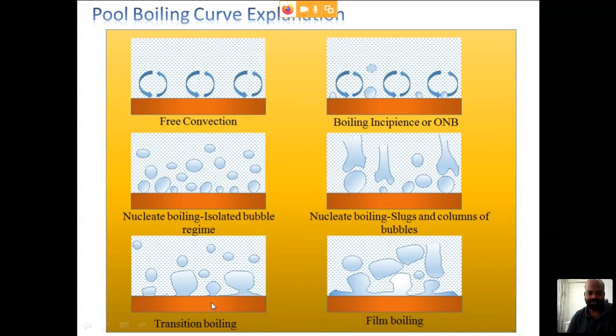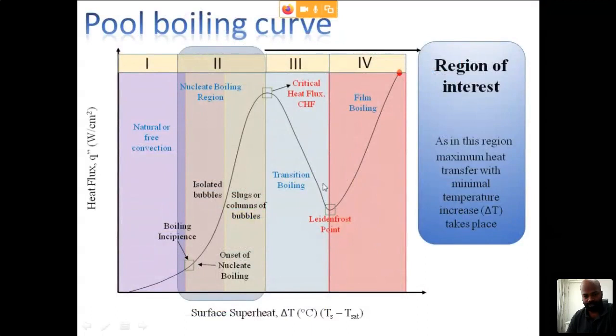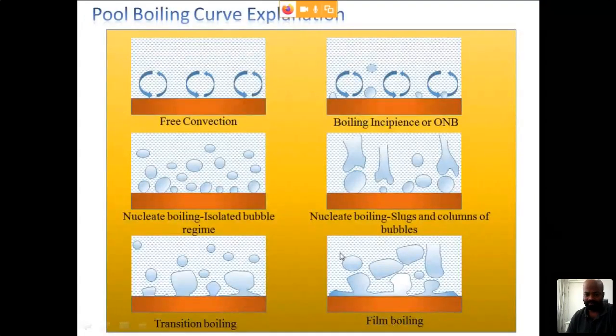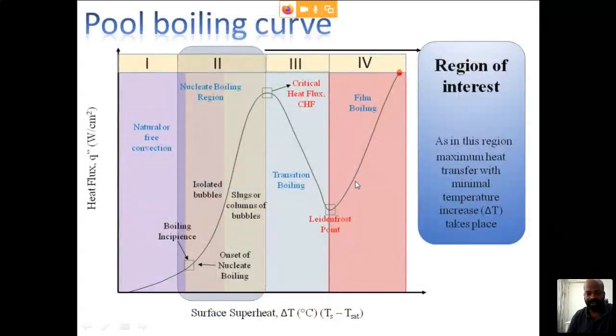Then it comes to transition, where it transitions to the film boiling region. This transition region is very unstable, and it takes place between the nucleate boiling region and the film boiling region, and that's why the heat transfer is very low in this region, and you can see in the pool boiling curve the slope is decreasing again. But when the temperature goes to a very high value, radiation comes into action in the film boiling region, and the slope again increases, giving a very high heat transfer value.